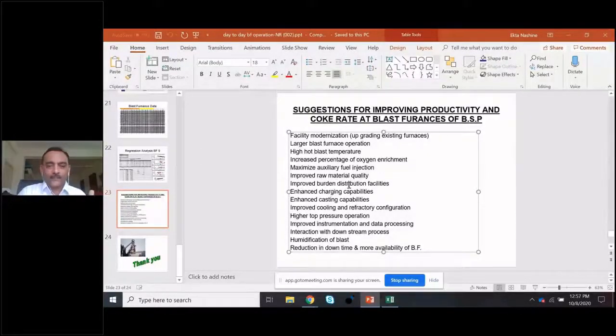There are probes on the top of the furnace. The gases going out of the furnace will show the temperature in different zones. So if you feel this zone is not active, we can improve coke in that area, or if it is highly active, or channeling happened, for that we do the distribution. Most of the time a common distribution we do: one layer of coke, one layer of iron ore, layer of coke, layer of non-coke. One by one we charge inside the furnace to maintain proper permeability. So this distribution part, if you are able to improve the charging capabilities,